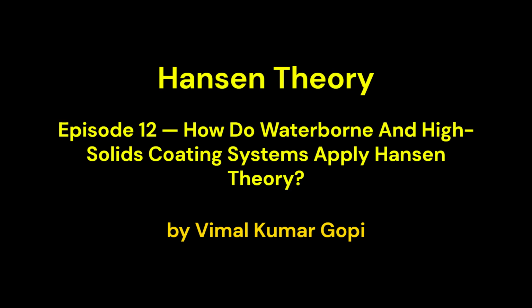Next, high solids coating systems. High solids formulations reduce VOC content by increasing polymer fraction and reducing solvent. Challenges include high viscosity, reduced molecular mobility, difficulty in pigment wetting, and cross-linking limitations due to diffusion constraints. Hansen Theory provides predictive control. Solvent selection or co-solvents maintain RED less than 1, enabling polymer and pigment compatibility. Additive selection and ratio optimization ensure wetting, dispersion, and curing despite reduced solvent volume. Multipolymer and multipigment interactions are balanced using weighted coordinates in Hansen space.